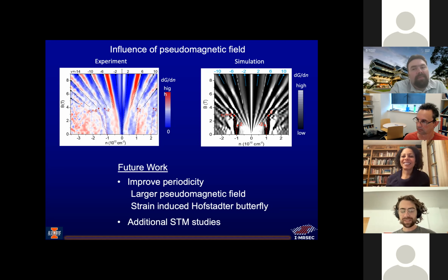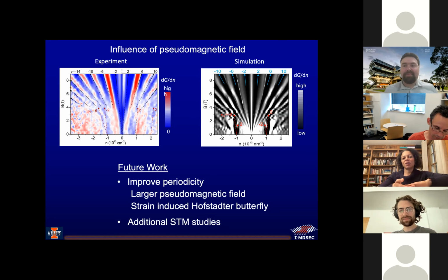I think it's interesting. It's just that it's been hard enough to see the effects that we didn't want to change too many parameters. So we're almost waiting for someone to tell us, hey, if you could do this on a flat particle, then you'd see these other cool things. Or if you could make something that's elongated and strained in one way and not the other, you could do it. The other thing is, we're limited because the graphene is just being pressed on. So the graphene sticks where it wants to stick. And we're not really controlling the area over which it sticks and the area over which it's being pinned. So if we start trying to do funny business with elongated particles, we don't know if it's actually sticking uniformly, even if we make particles that are long in one direction, because it just depends on how it adheres and what the local strain is.